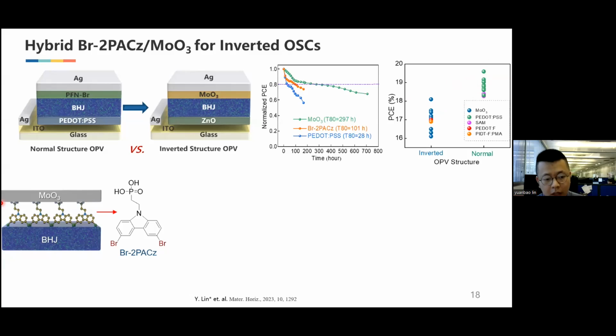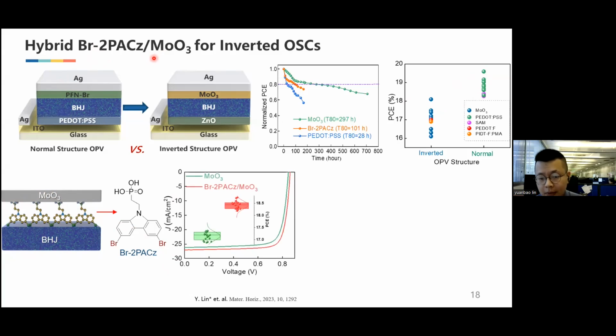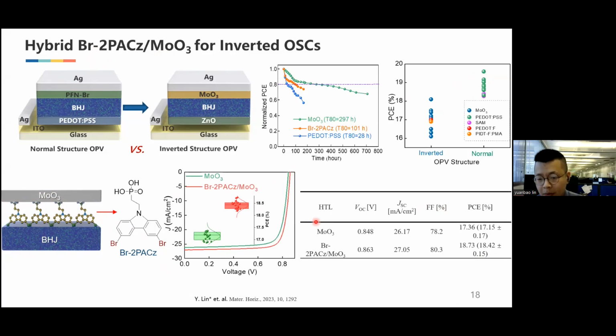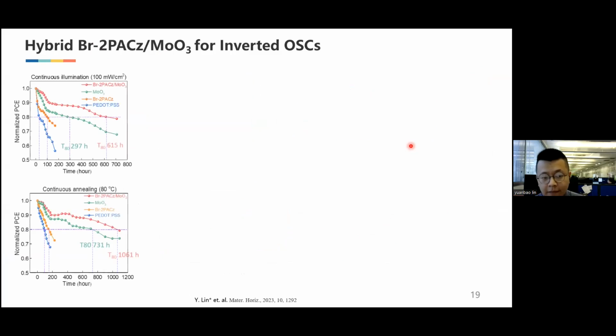So in my other work, I tried to put the bromide 2PACz solution between the bulk heterojunction and molybdenum oxide. We call it hybrid bromide molybdenum oxide, because we cannot determine if it is a self-assembled monolayer. So we call this one a hybrid molybdenum oxide and bromide 2PACz HTL. As a result, the VOC and the fill factor are slightly increased as compared to only molybdenum oxide. We also tested the lifetime of this material. As we can see, the T80 lifetime with continuous measurement can increase to around 650 hours, and for annealing stability, it also increased a lot.